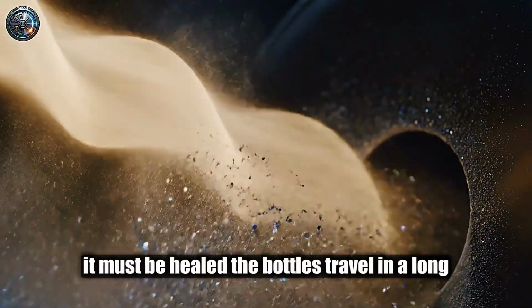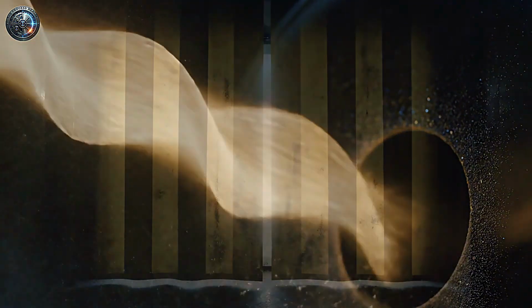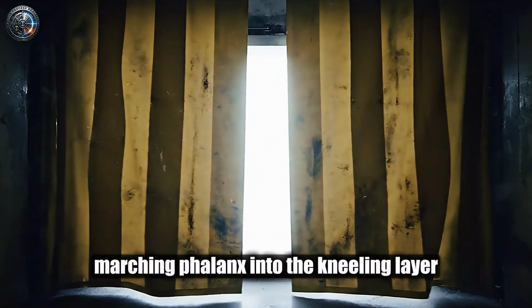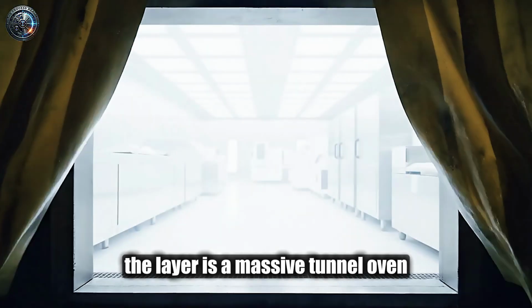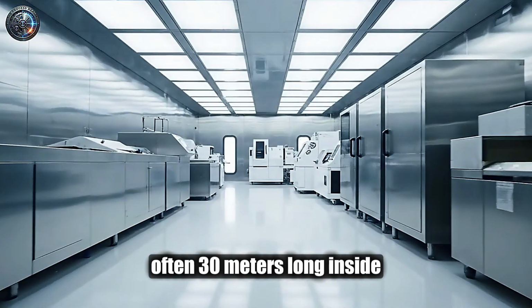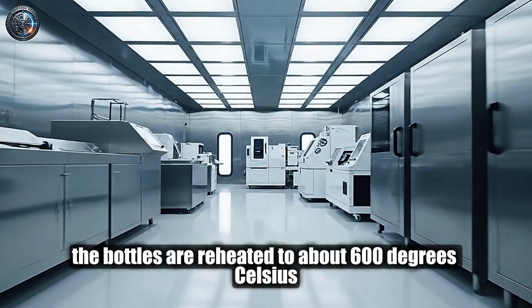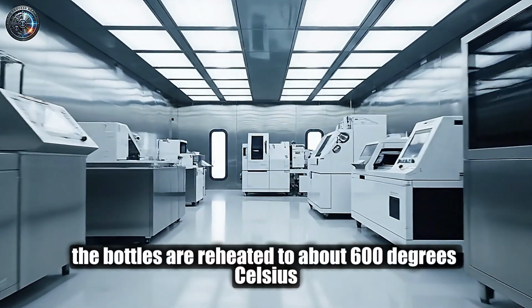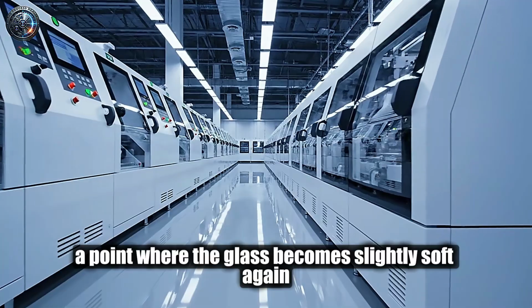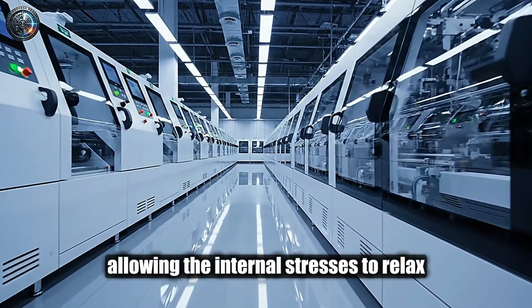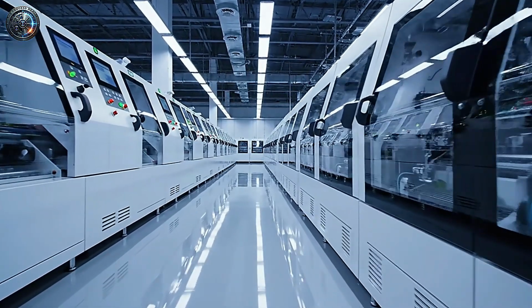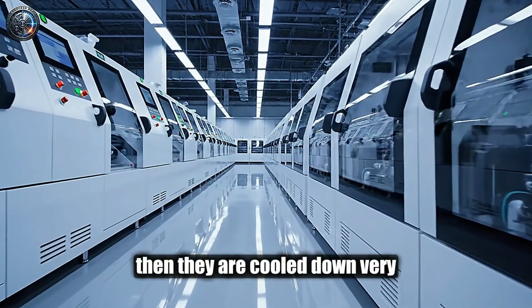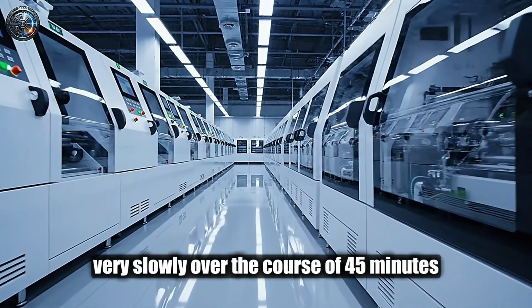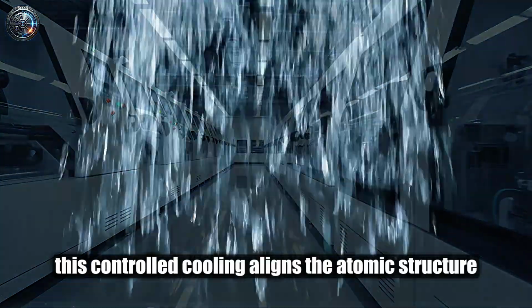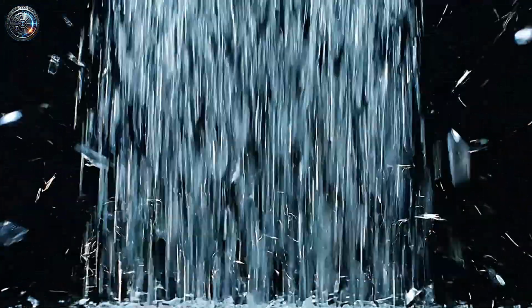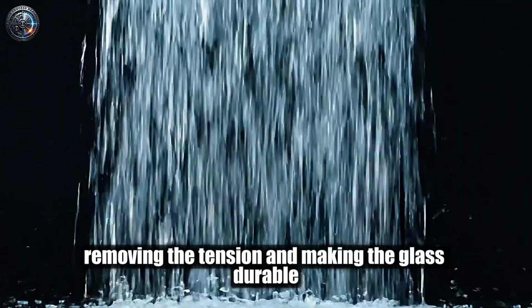It must be healed. The bottles travel in a long, marching phalanx into the annealing lehr. The lehr is a massive tunnel oven, often 30 meters long. Inside, the bottles are reheated to about 600 degrees Celsius, a point where the glass becomes slightly soft again, allowing the internal stresses to relax. Then, they're cooled down very slowly over the course of 45 minutes. This controlled cooling aligns the atomic structure, removing the tension and making the glass durable.